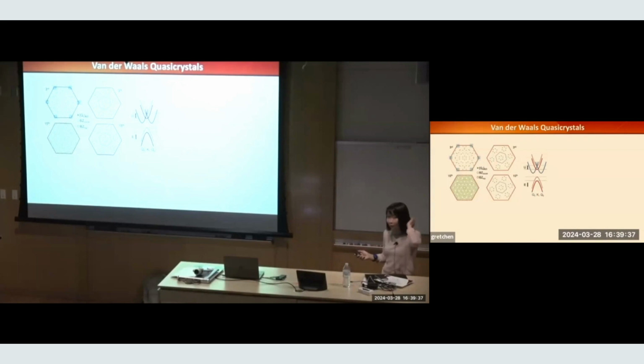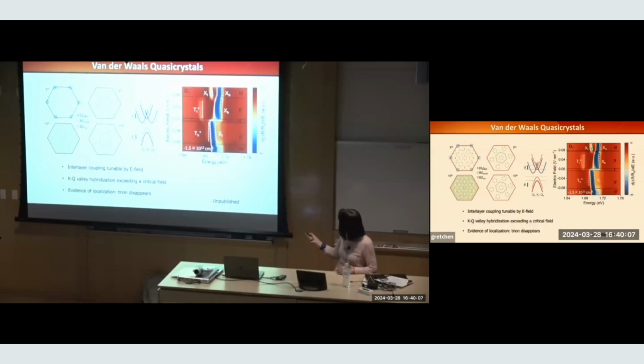show you that we can actually see signatures of them in optical spectra. What's special is this strange atomic alignment in real space. In momentum space, you can bring the K valley and Q valley, again a high symmetry point, to infinite proximity to each other if you consider what's called high order Umklapp scattering. So you have this very special KQ coupling from different layers, and they give us really rich optical spectra.